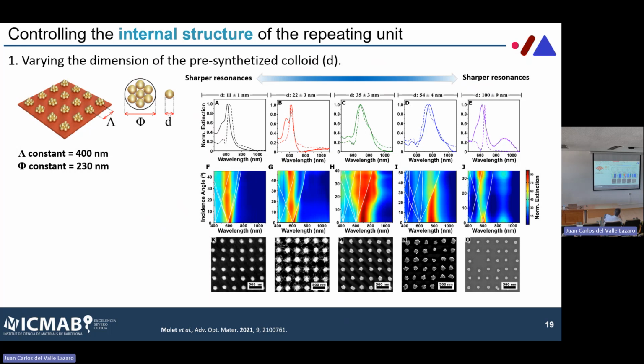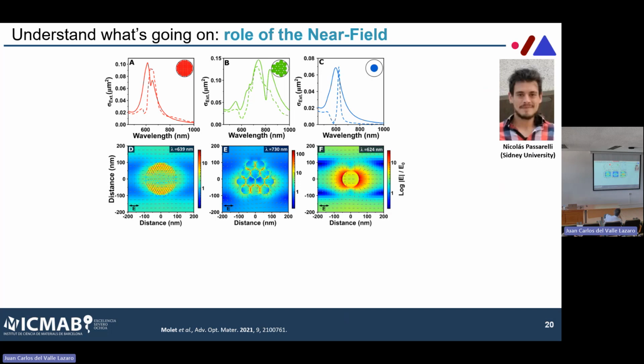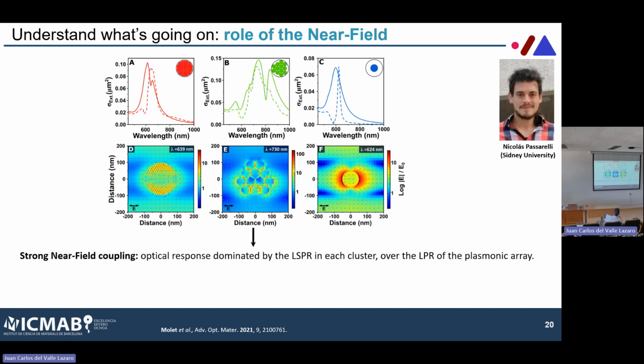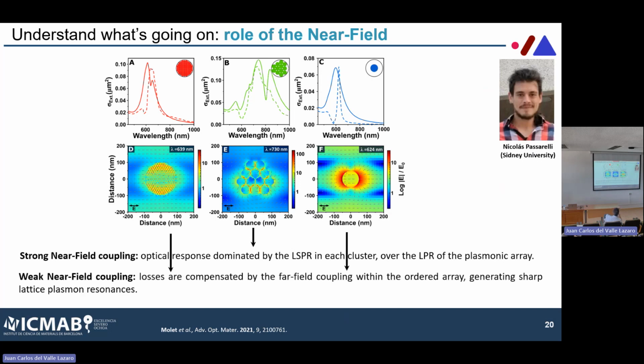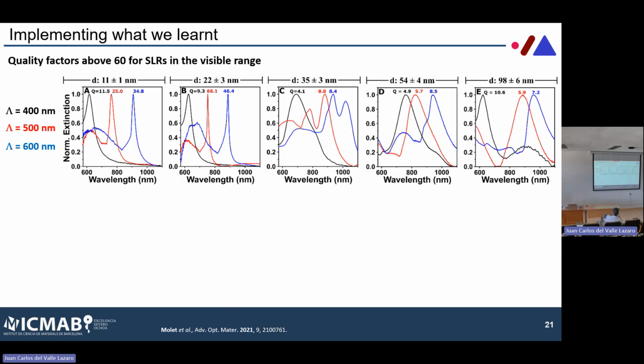And so we tried to go in the other direction, making my particles smaller and integrating more particles. We started to see that going towards smaller particles, we also saw some sharp features, and so we started to understand why. It turned out that moving away from the first condition that I showed you, where you have strong near-field coupling, you can move into the other two conditions where you have weak near-field coupling. This seems a little counterintuitive, but when you have very, very small particles, the near-field coupling is also much lower. So the near-field coupling is lower on either side. But with very big particles, where you try to put one particle in each position of the array, this is very hard to do with our technique of templated self-assembly. Instead, this one is very, very easy. So by combining everything that we knew, we optimized the system.